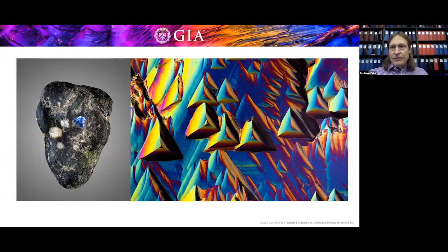I think this was one of Nathan's photos, but it's showing essentially the same features, these triangular depressions. And so we kind of know that they are etch pits, essentially, because the geometry of those triangular features is constrained by the corundum crystal lattice, which is trigonal in nature. And so when that corundum crystal lattice is being eaten away, the shape of those etch pits is often constrained by the crystallography of the corundum itself, giving you those triangular pits.